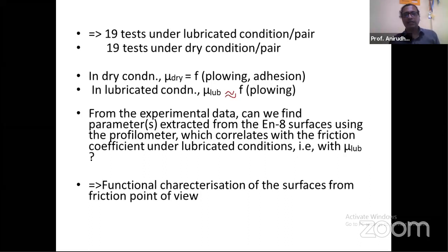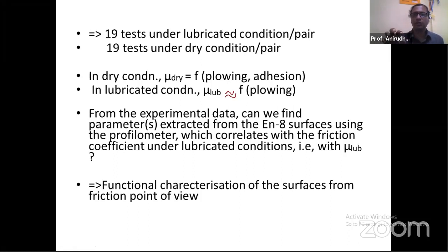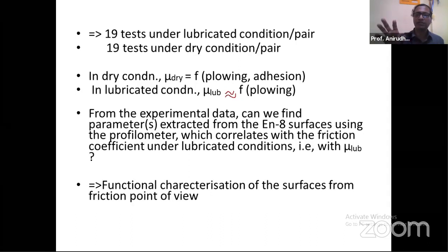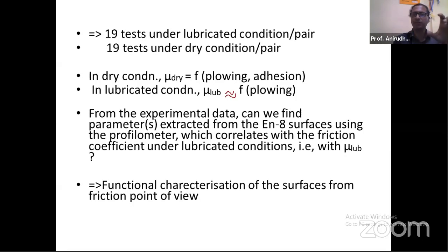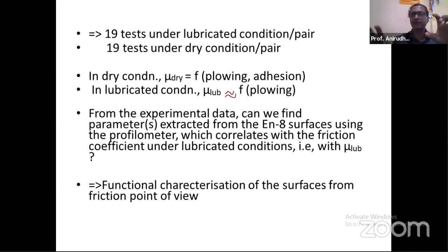And then we wanted to see, from the experimental data and from those features captured using the profilometer, whether we could correlate the features of topography with the values of coefficient of friction that he registered from his sliding experiment. That was the challenge given to me: can you look at those surfaces, extract features from those 19 different surfaces, correlate them with the friction found for those 19 tests, and come up with some magic parameter which can explain this friction in terms of the roughness parameters obtained from the profilometer?